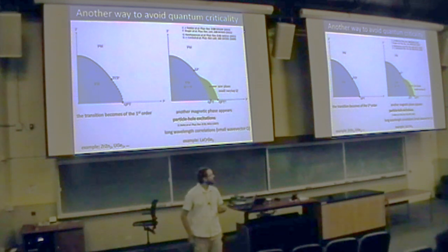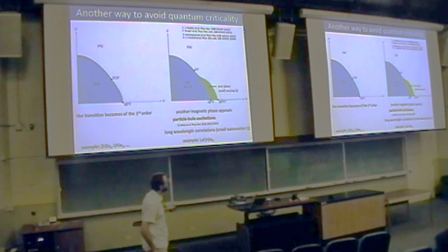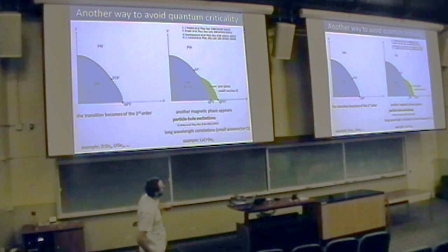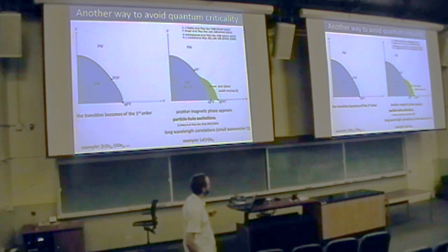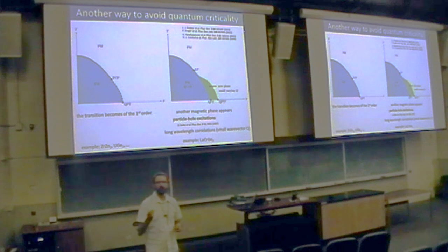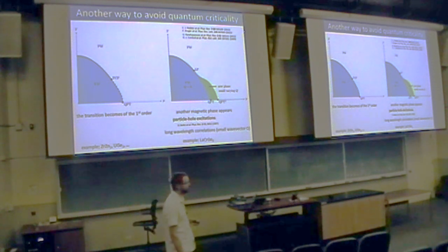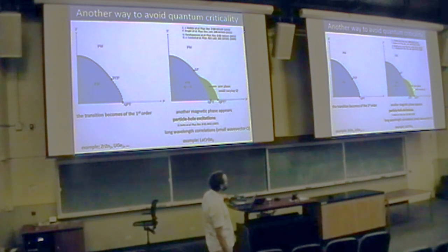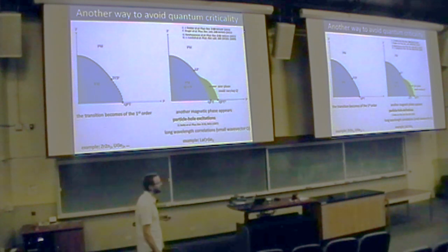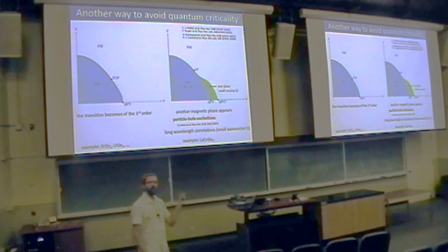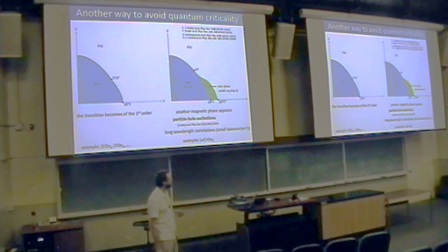And what they find is a new possibility for the phase diagram, where you have this ferromagnetic state corresponding to Q equals 0, and then you have this new phase that has a small wave vector Q that can vary in this region here. It can vary with pressure and with temperature. And this new phase starts at a point that we call the Lifshitz point, and it can be like a spin density wave, or helical ordering, conical ordering, and so on.